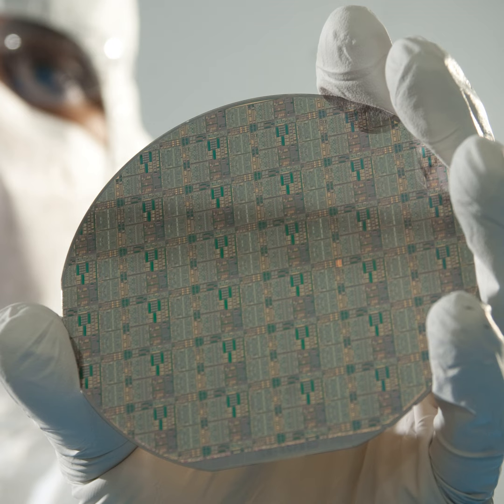What's unique about their capability is the size. Single crystal diamond is known in smaller diameters, maybe 10 millimeter squares. But in order to achieve the program goals and where we want to head, you really need a process that's consistent with larger wafer diameters, 50, 100 millimeters, et cetera. So they are providing that. I also mentioned the bonding. What's key here is to get that bond to the diamond as thin as possible, and the polishing of the diamond down to less than a nanometer of roughness is absolutely critical for this program.